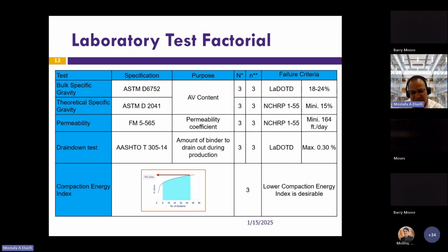So the tests that we did, some of them are volumetric. So we measured the air void, and we measured the permeability of the mix based on the Florida DOT test method. And the minimum requirement, so there was a large NCHRP study that was conducted, and it recommended a minimum permeability of 164 feet per day. The drain down test was conducted to assess how much asphalt will drain during production. We looked at the compaction energy index, which is a method to assess how much compaction effort you would need during the mix compaction.